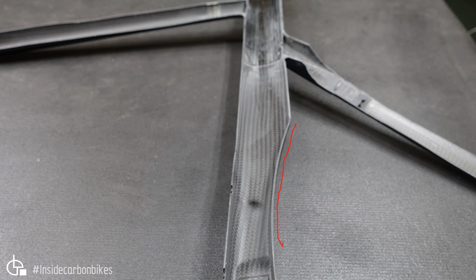The ultimate structure is in unidirectional, knowing all the loads and optimizing your fiber angles to meet those loads, so this is less than optimum from that point of view. However, from a practical point of view, you don't have some of the production faults you can have with unidirectional, like planar voids. In this process, due to the resin injection pressure, you won't get laminate voids if it's been done and monitored correctly. The void can't form under that high pressure resin injection process.